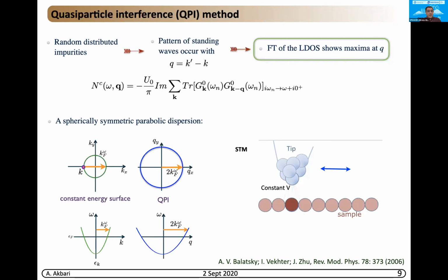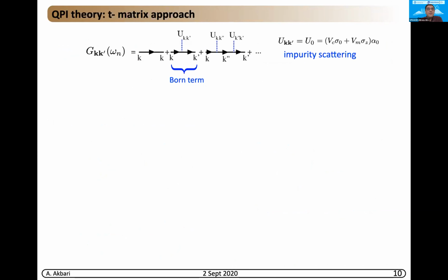For example, if you have a normal state feature with parabolic dispersion, whose constant energy contour is given by a circle, we expect to see a circle-like feature in QPI as well, but with a momentum 2 times larger than the original momentum. You can also detect similar dispersion in QPI in the same fashion. So in principle, for our model, we just need to find the total Green's function, and by looking at the imaginary part of that, we can detect the modulation of the density of states.